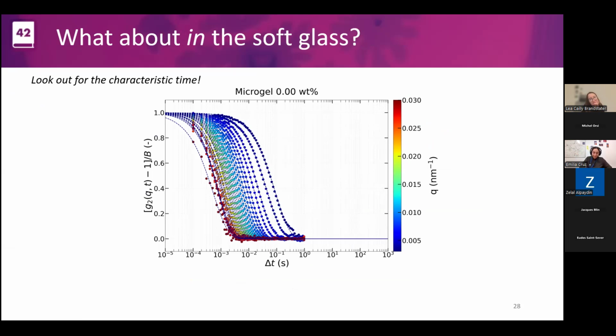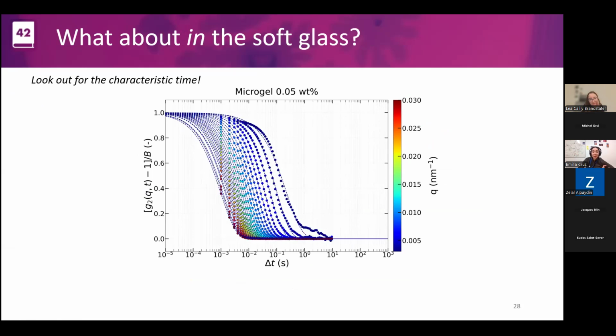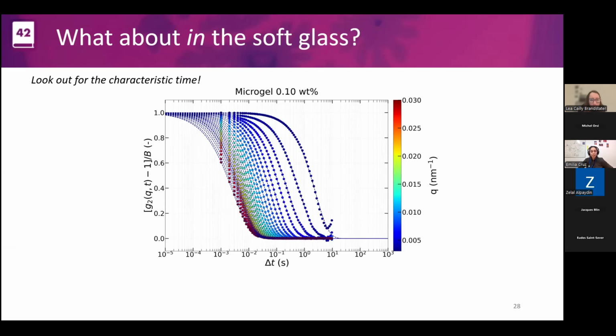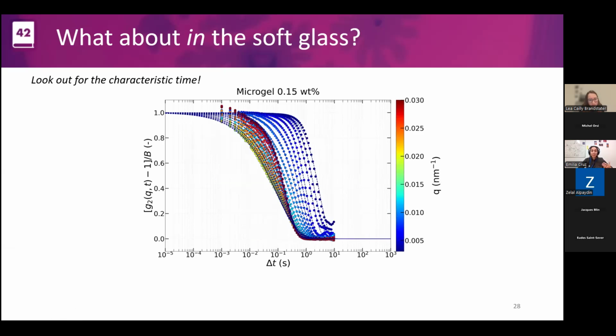And now we do the experiment in the soft glass, and we want to know if those pockets are really moving inside, if the particles are moving inside of the microgel. So we have the microgel at very low concentration, and we see that the particles seem to still be Brownian, but we know that they're not in a pocket yet. But okay, they're being a bit slowed down because the characteristic time is shifting to longer and longer times. We put more microgel, and we see the same.